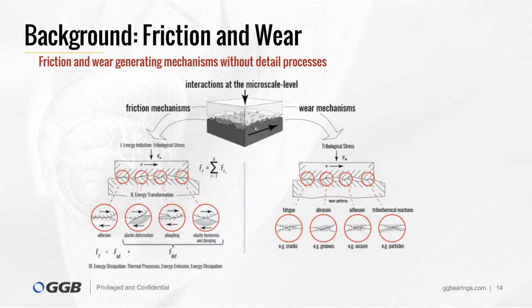Abrasion often leads to grooves and scratches because the harder asperity penetrates into the softer surface and furrows it during the relative motion. Adhesion often causes seizure and material transfer because of the formation and destruction of adhesive bonds. Chemical reactions can lead to particles which can also act as an abrasive in the tribological contact.